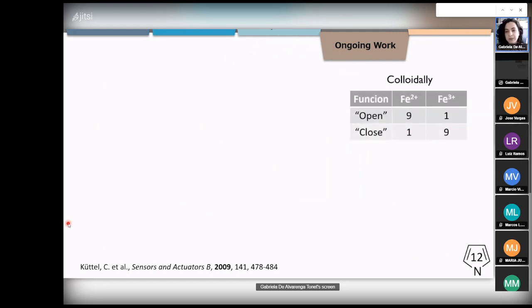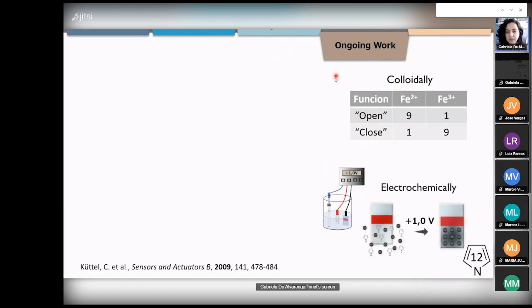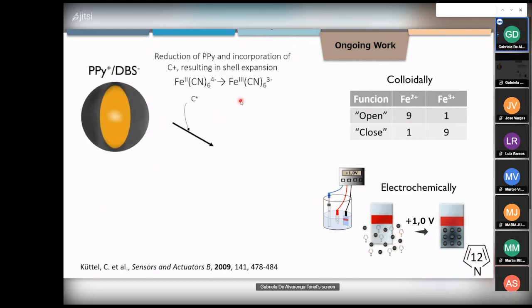And we chose two types of stimuli. One, where the capsules would be submitted to reducing and oxidizing solutions. So this would be done colloidally with the capsules dispersed in solution. And we actually formed a solution that would open and one solution that would close the capsules. This part was performed in Spain. And then the next step, which is what I'm doing right now, is to repeat this opening and closing of the capsules, but electrochemically, by immobilizing these capsules in an electrode and then oxidizing and reducing them electrochemically. So basically, just to remind you of that example, we have a capsule with polypyrrole and DBS.